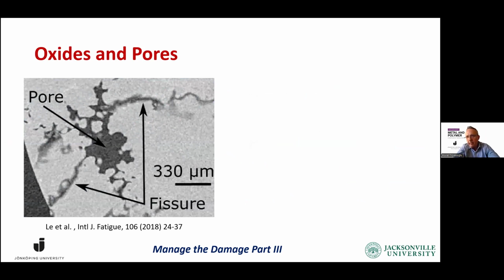So from then on, I started looking in the literature. Then we started looking at some experimental results that we're going to show. But there is always an oxide next to a pore. And in fact, calculations show us that it's impossible to nucleate a pore, either homogeneously or heterogeneously in liquid aluminum. So the only mechanism available for a pore to form is a pre-existing surface. And that pre-existing surface is the bifilm. So anytime we have a pore, there is a bifilm right next to it that remains unopened.